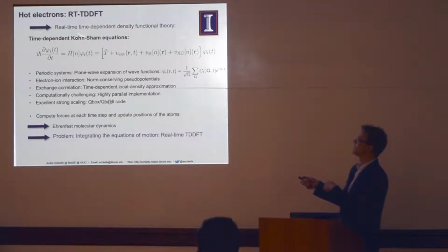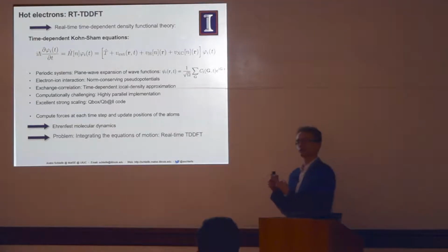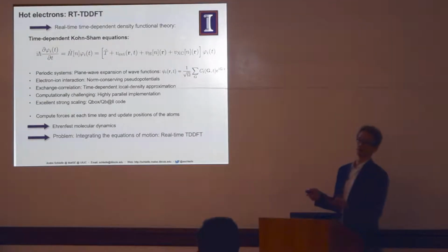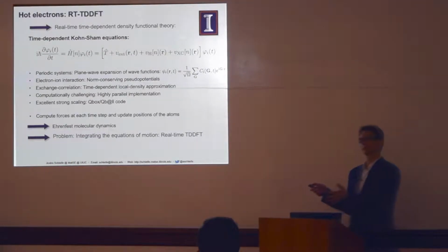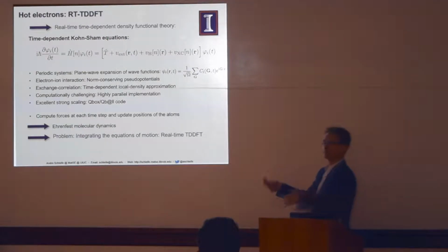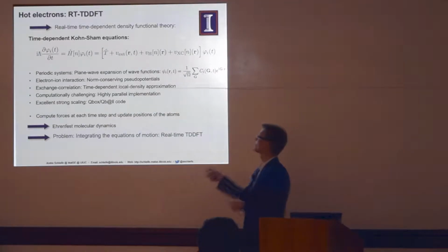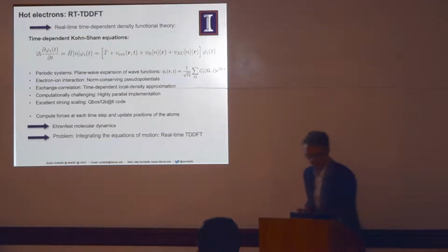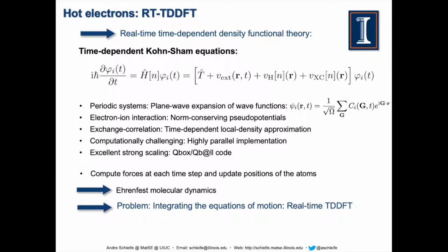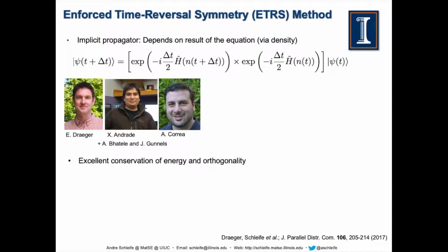In this case, there's another flavor of time-dependent DFT, which is called real-time propagation. That's what we're doing. So we start with an initial condition for these equations that comes from density functional theory, and then we propagate in real time, going from time step to time step to time step. So we propagate these orbitals in real time. That in itself is actually an issue, and it's an unsolved issue, meaning many people are trying to find integrators, numerical integration techniques that can achieve this time stepping of these equations.